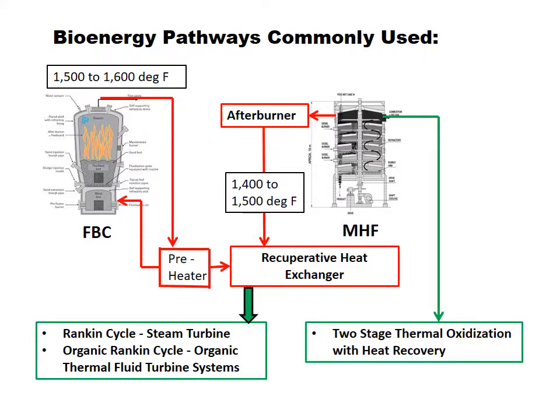So, with these incinerators, how do they recover bioenergy? Well, in the fluidized bed, it burns in what's called the freeboard or the upper zone at about 1600 degrees. Typically on a fluidized bed, there's what's called a preheater. They recover some of that heat from the exhaust and pipe it back into the wind box, or the bottom of the fluid bed, to conserve energy and heat in there. It takes about half the heat, by the way. But there's still enough heat left over to go to a recuperative type heat exchanger. And from there, you can go to a steam turbine or an organic Rankine cycle. I'll touch on that a little bit. I have a lot more information.